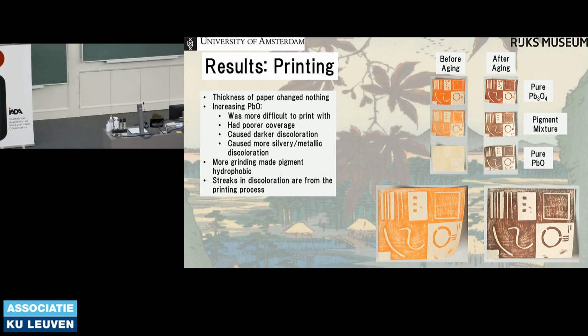During the aging of the prints, it was also found that the more lead monoxide was added, the darker the discoloration became. It was also found that this discoloration was much more likely to become silvery and metallic the more lead monoxide was added. I should note that there's no evidence the Japanese printmakers used lead monoxide as a pigment, but the quality of the final print produced and how much it discolored may have been affected by how much lead monoxide was apparent as an impurity. It was also found that the grind of the pigment was significant during the printing process because over-grinding the pigment actually made it hydrophobic and very difficult to mix with water, and I had to work the pigment a lot more in order to get a print that was of quality enough for me to use for the research.